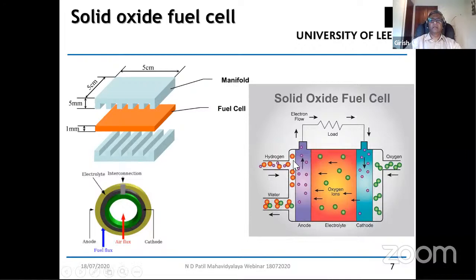So you have the hydrogen coming at the anode, forming water, and the free energy change for the formation of H2O from hydrogen and oxygen, which are traveling from the cathode after being reduced at the interface through the electrolyte across and combining with hydrogen to form H2O. So the free energy change basically gives you the theoretical voltage drop across the electrodes, which will then be converted into power when you have a load connected to the cell. And the electrons flow in the external circuit from the anode to the cathode, and the circuit completes.